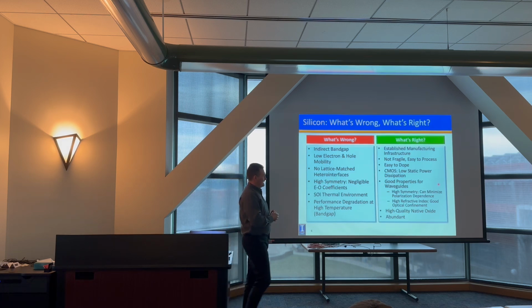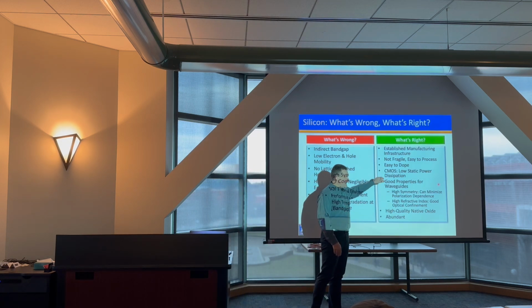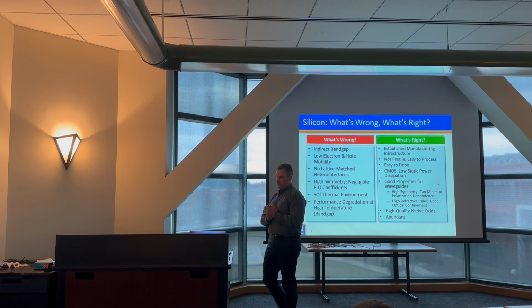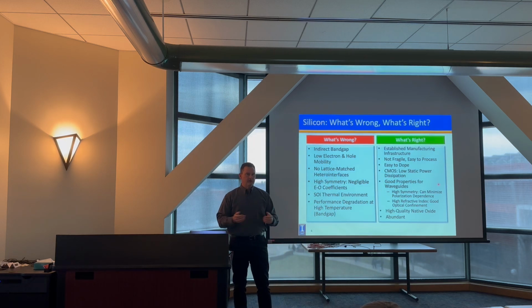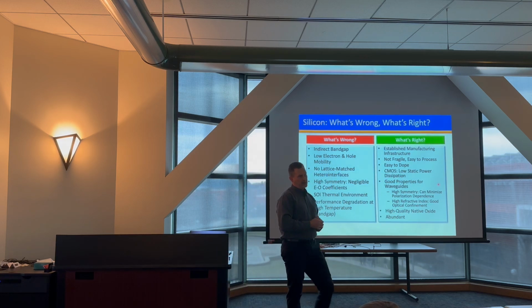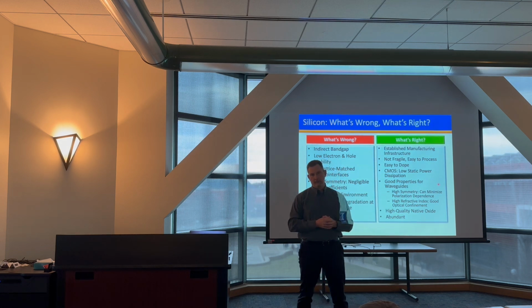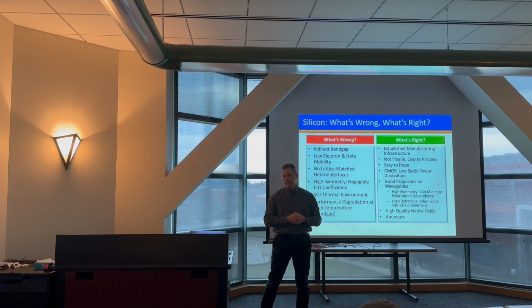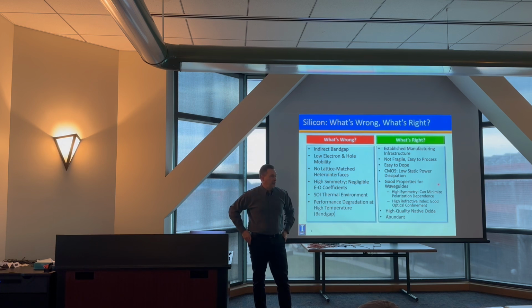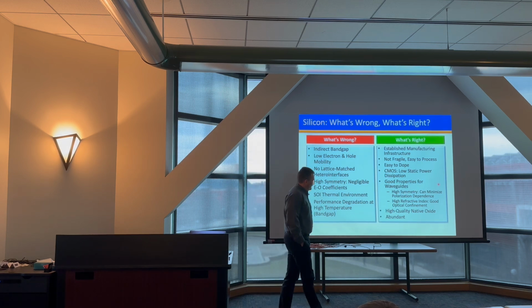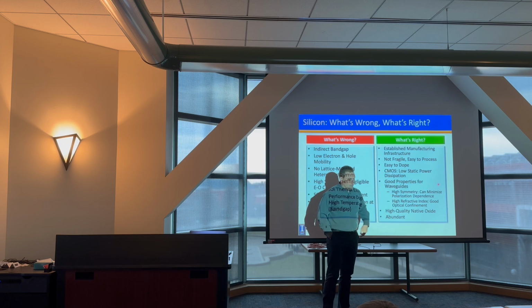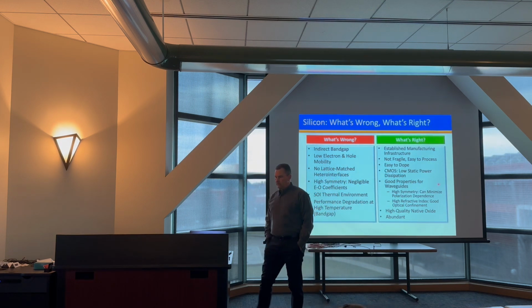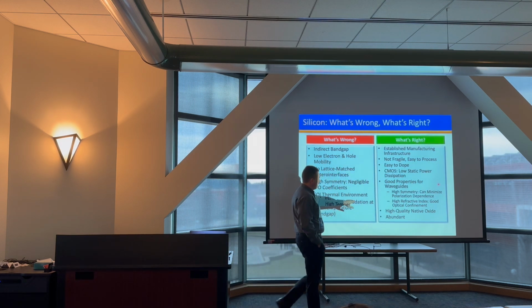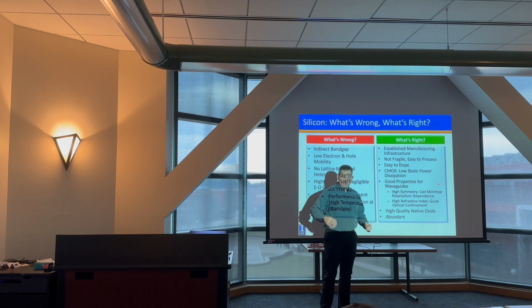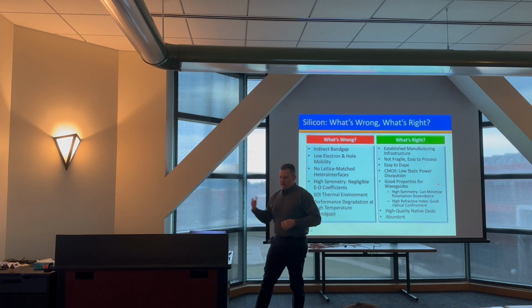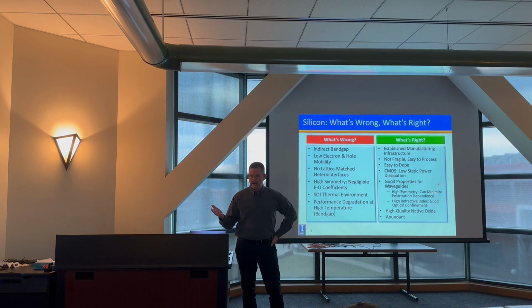Obviously CMOS itself is powerful, with very low static power dissipation. That's one of its advantages. From an optical perspective, silicon is great for making waveguides if your wavelength is above about 1.1 microns. Below that, it's not good, it's opaque. And one of the reasons it's good for waveguides is because of its symmetric nature, you tend to have minimal things like polarization dependence. It's got a high refractive index, so there's good confinement. And the other thing about silicon is that it's got a high quality native oxide.